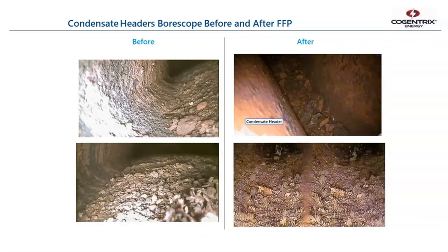Here's a picture of the borescope of the condensate headers coming out of the ACC before and after the amine-based filming products and the non-amine-based filming products. But what they don't do is clean up your dead spots. Chip scale that's there is still going to be there. It's going to take a long time.